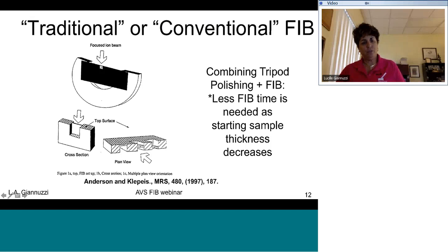So here you see you can mount this in cross section and FIB mill a sample, or by mechanically polishing the sample at 90 degrees, you can make plan view samples. And the advantage to this now is, say this slotted half grid, you've got 2 millimeters of open area. So now you've got 2 millimeters of material where you can FIB mill multiple windows across here. So it's advantageous in this way that you can make multiple samples up and down here.